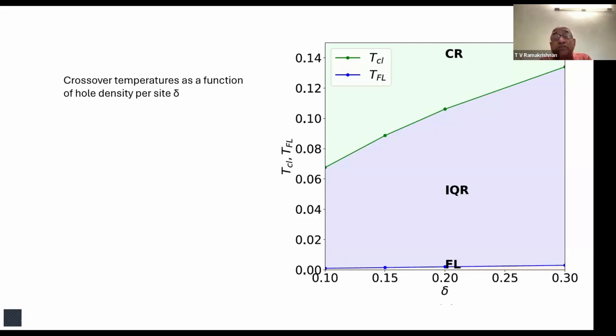Obviously, if you have a lattice, there are a large number of arrangements of this kind, and that gives you the entropy of the system. So this entropy is also very well known, and you can calculate this entropy. This is an entropy of charged systems, and therefore it should be relevant in thermopower. And indeed, it turns out that in strongly correlated systems, the thermopower reaches this classical limit at surprisingly, astonishingly low temperatures, and the value which it has is roughly the same as what you would have if you assume the electrons to be classical non-hopping, strongly correlated objects, 1 electron per site.